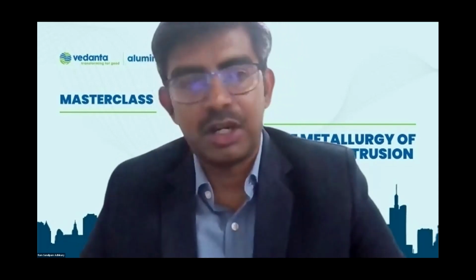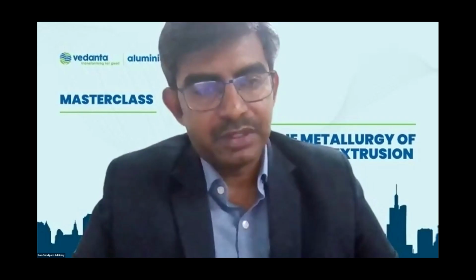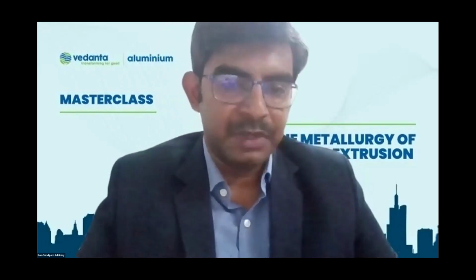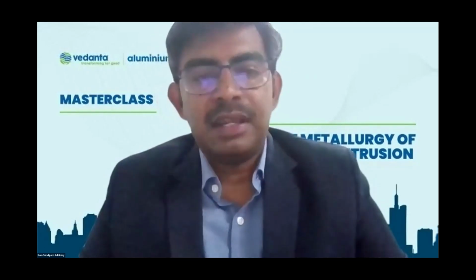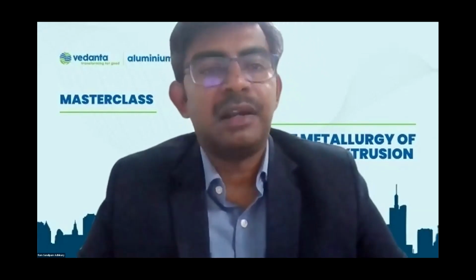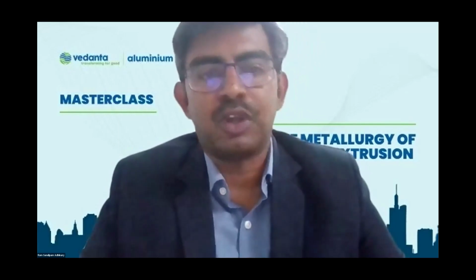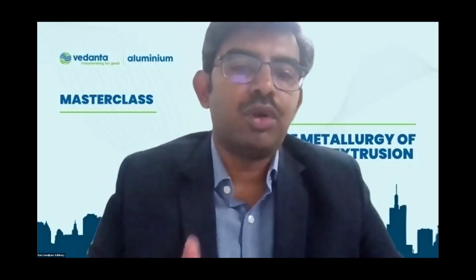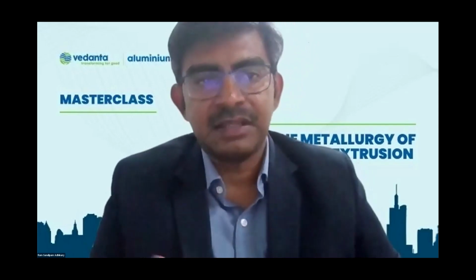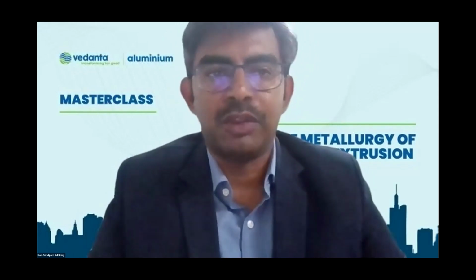Sure, Manish. I think from a billet producer's perspective, if you look at where it can be generated, of course, there are two sources. Either it will be from the hydrogen or the porosity that is coming while casting the billet, or second, if there is an uncontrolled homogenizing process, meaning the temperature is more than what is being set up, or the time for homogenizing is exceeding the design time. Then one could find there is a porosity or air bubble formation outside the billet layer, which can eventually pass on to the extrusion process as well. But I think there is more to the extrusion process than to billet in these cases. So Johnny, if you'd like to please comment, elaborate on that.